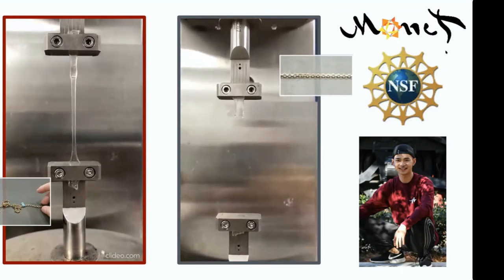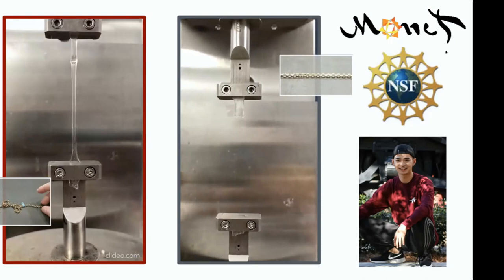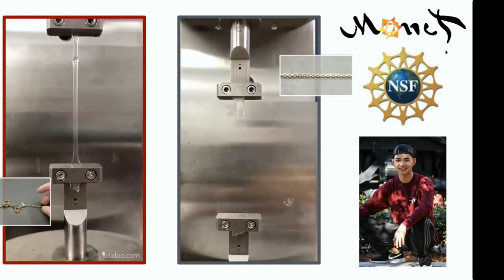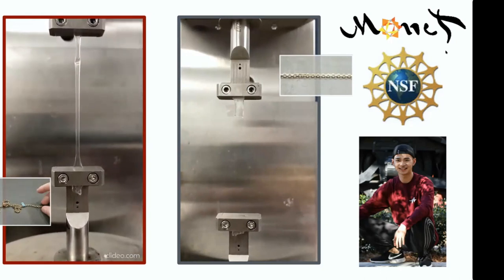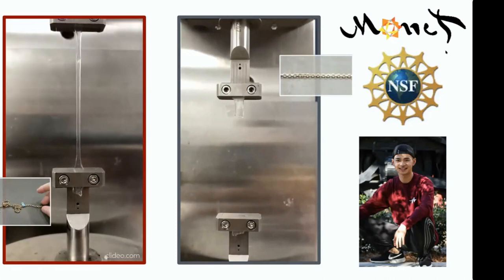But at that same stretch, at that same strain in the MONET network on the left, the hydrogel survives, can be stretched further and further and further until it breaks, but at a much, much later point than the sort of unmodified traditional kind of polymer network.